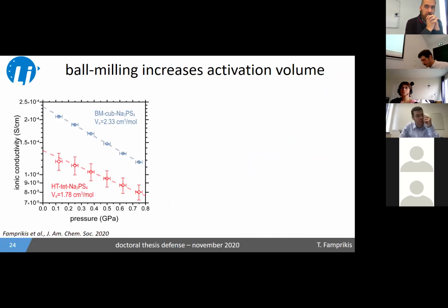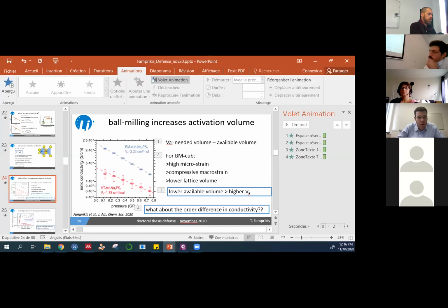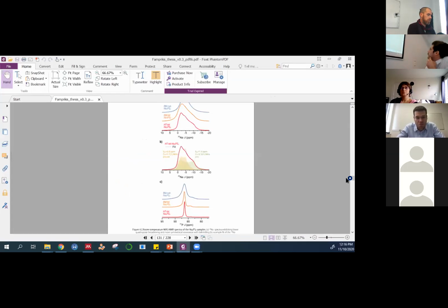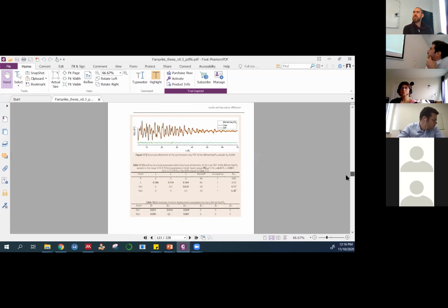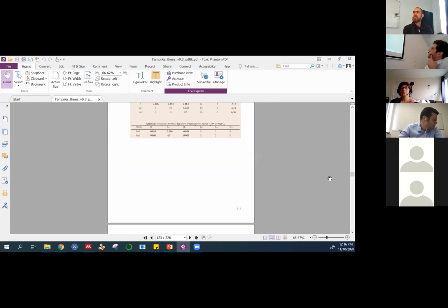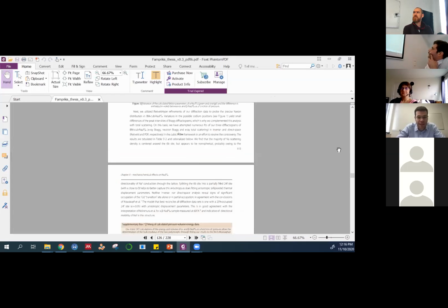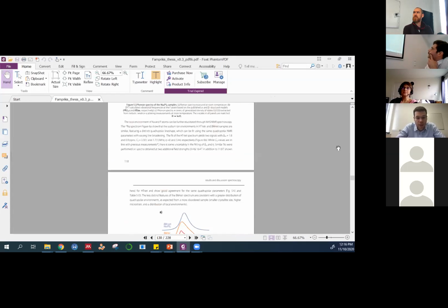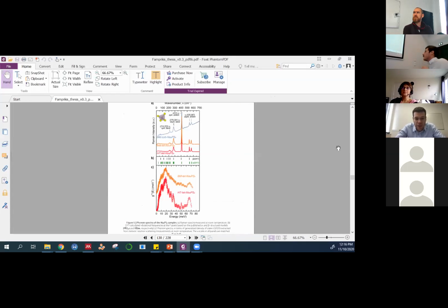Another thing that I found really interesting, and this is in your thesis on page 118, you quickly showed the phonon DOS earlier as well, where you show your phonons flattening out at higher temperatures. But when you directly compare your ball mill and the high temperature NPS, just the phonon spectra, you have there, you go.